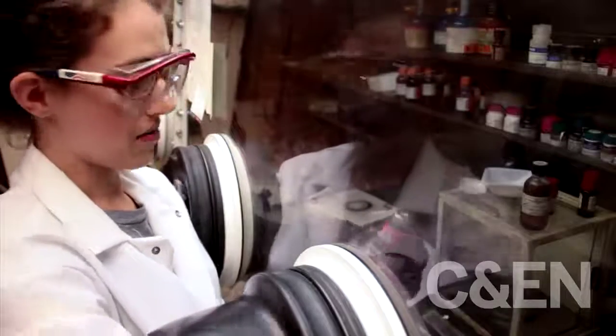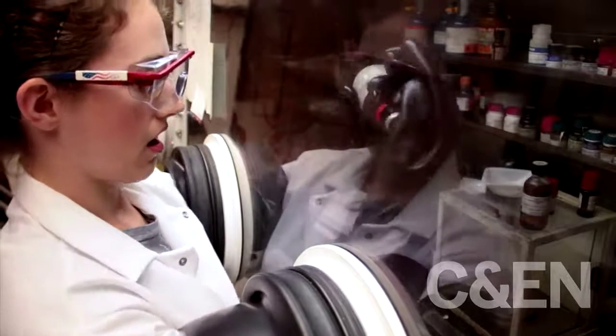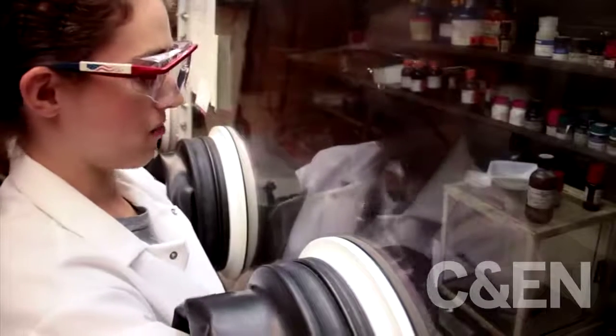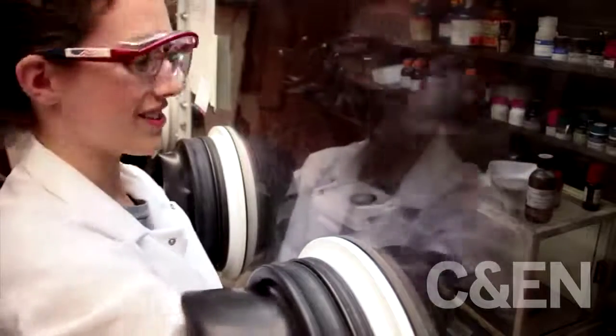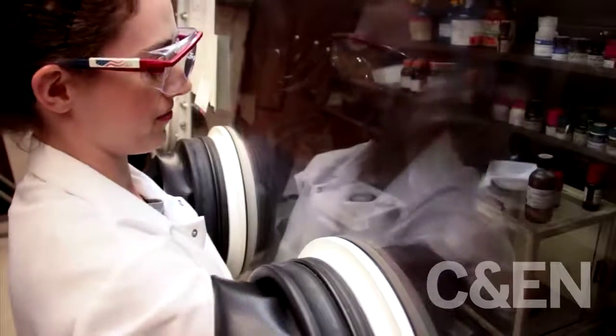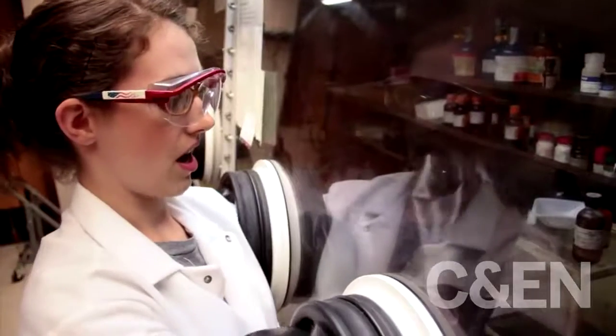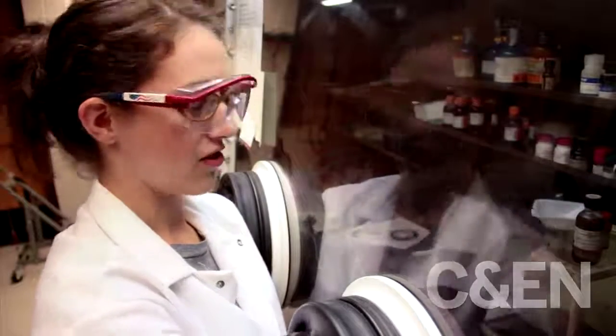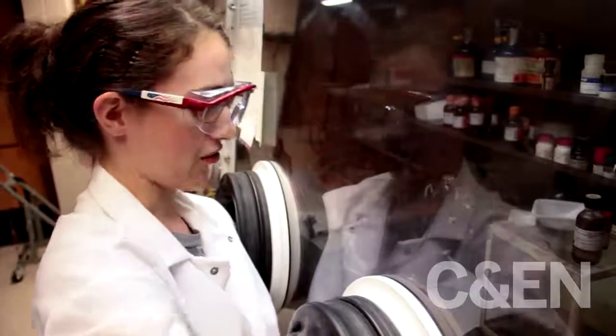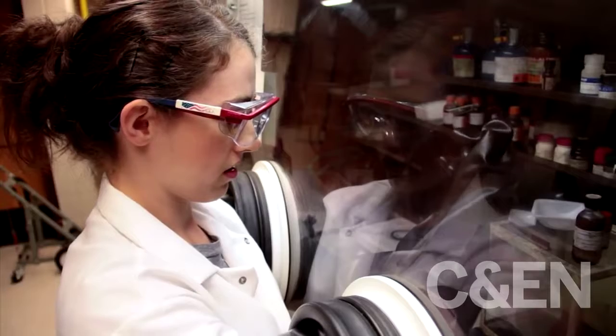So first I'm just measuring the selenium powder, but the selenium is the component that we add in excess. So now I'm just going to dissolve it in the TBP. And when I dissolve it, it is an exothermic reaction, so it heats up a little, but not to an unbearable amount. It takes a little bit of mechanical stimulation to get this to dissolve, so I just shake it up. So now I'm going to split this between two syringes so that we can inject it faster, and so that everything is injected more at the same time, and therefore it will grow to be about the same size. So now that these are ready, I'm going to get them ready to be taken out.